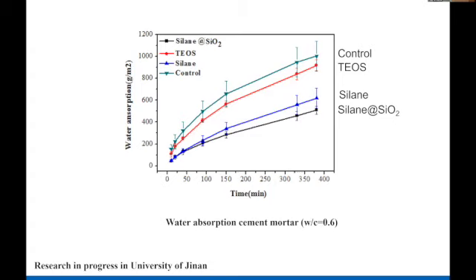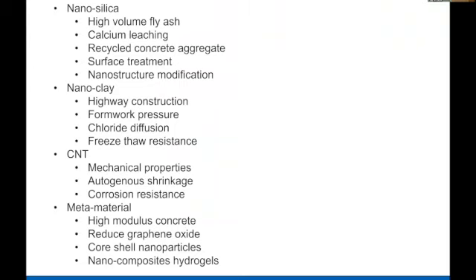So I think this is an interesting direction to go as far as application of nanotechnology is concerned. I want to summarize and then talk briefly about what direction we are going. Nanosilica, as I mentioned, is a widely used nanoparticle with many advantages in high volume fly ash and calcium leaching, in improving absorption of recycled concrete aggregate, in surface treatment, as well as in the modification of nanostructure. Nanoclay, I only talked about rheology, and as I said, it increases thixotropy, but people have also shown that addition of calcined purified nanoclay brings a lot of improvement in durability and other properties as well. Carbon nanotube, we talked about it, and briefly we talked about metamaterials.